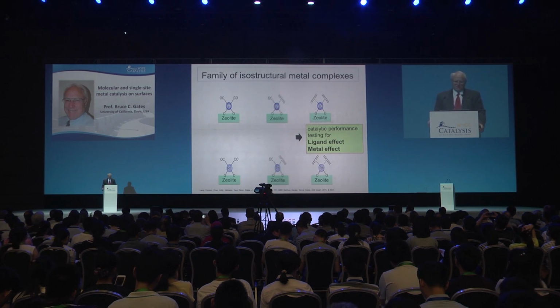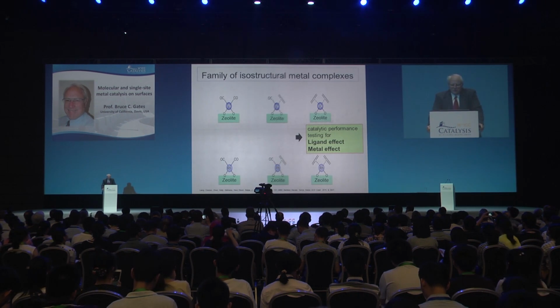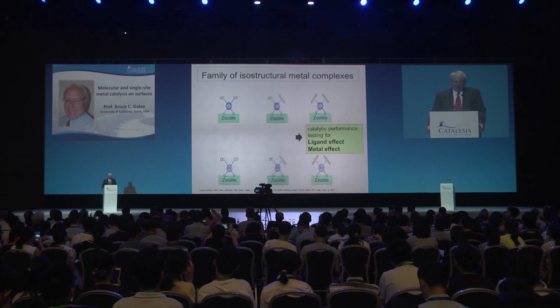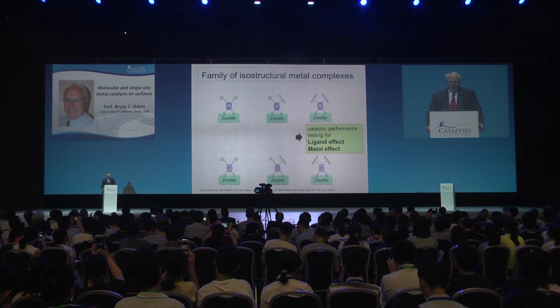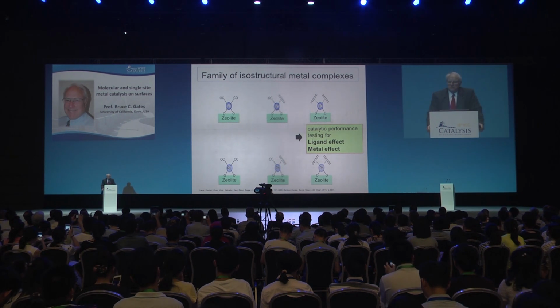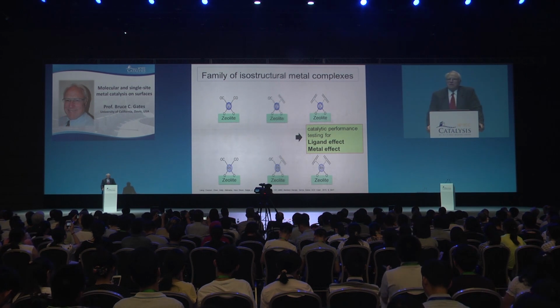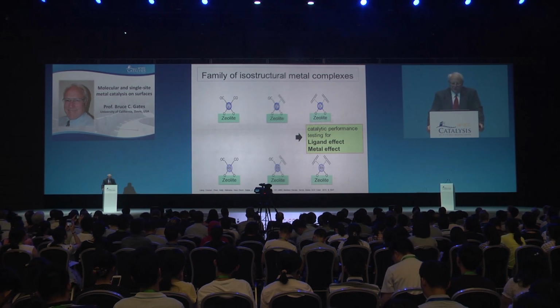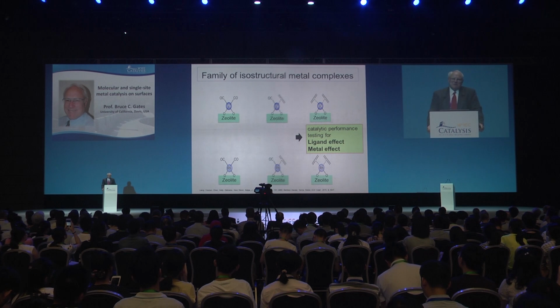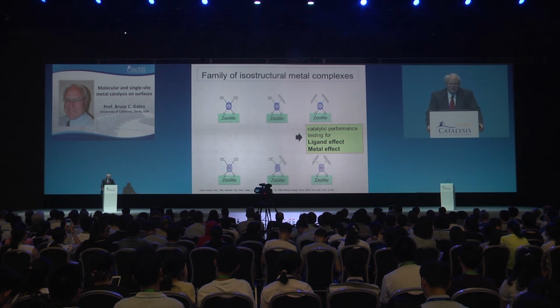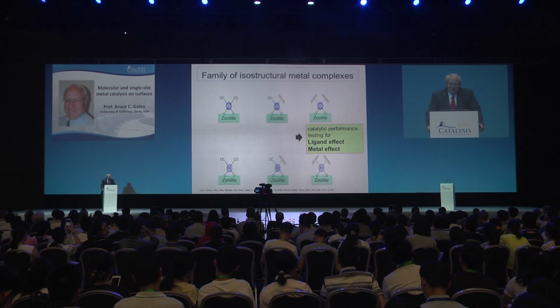So here's the family of pre-catalysts: the same zeolite support, with iridium and rhodium as the two metals. On the left, you see iridium or rhodium gem dicarbonyl. On the right, you see ethylene ligands instead of carbonyls. And in the middle, we systematically replaced one carbonyl with one ethylene.